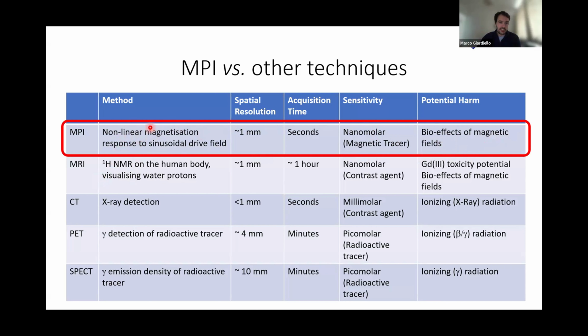So MPI looks at the tracer directly, whereas MRI is essentially, if people know what NMR experiments are, nuclear magnetic resonance, a proton NMR experiment on the body. So you visualize the magnetic response of water protons in various different tissues, and that can give you contrast. Again, it's a resolution of about 1 millimeter. They take much longer than an MPI because there's so much water in the body, you get a lot of background signal, and you have to do long scans in order to have your contrast. For that, you can add a contrast agent, typically gadolinium, which is what I did a lot of my previous work on. But gadolinium contrast agents themselves have some possible toxicity and all this kind of stuff.